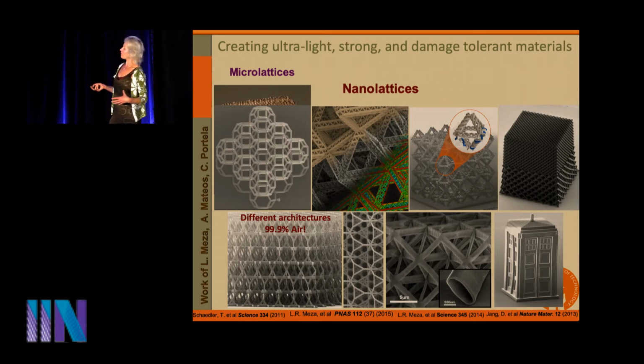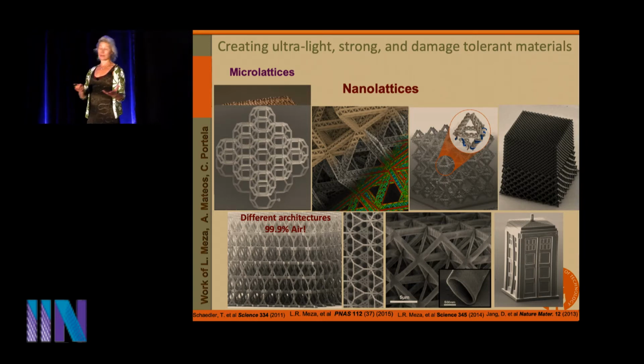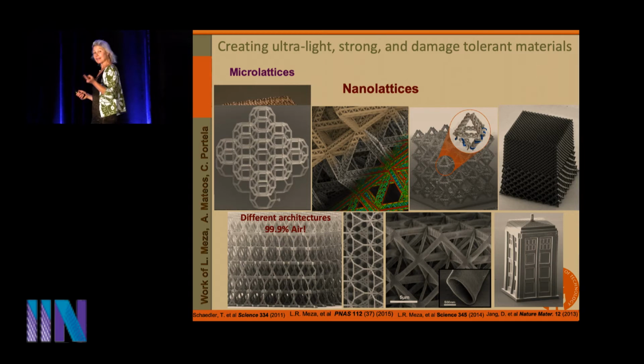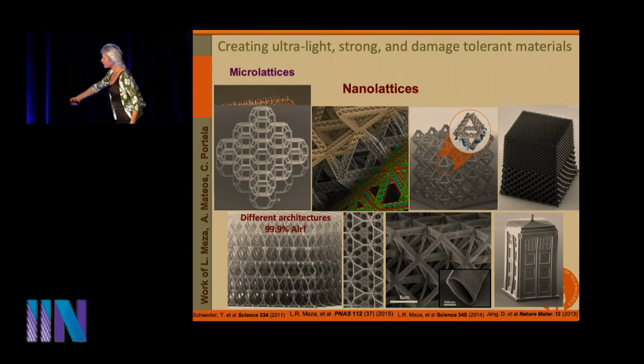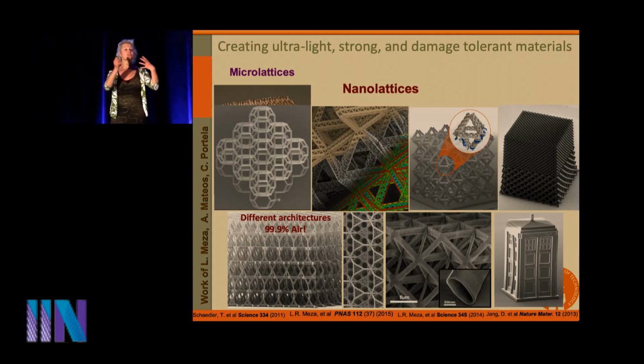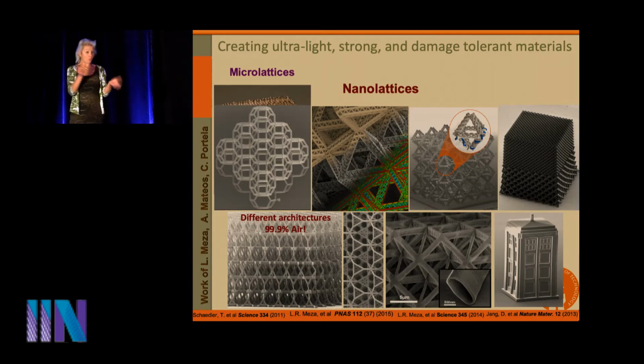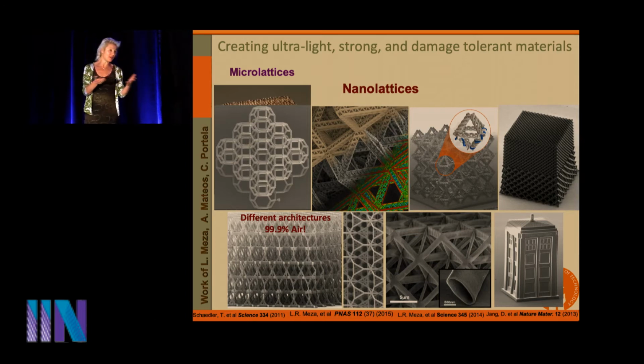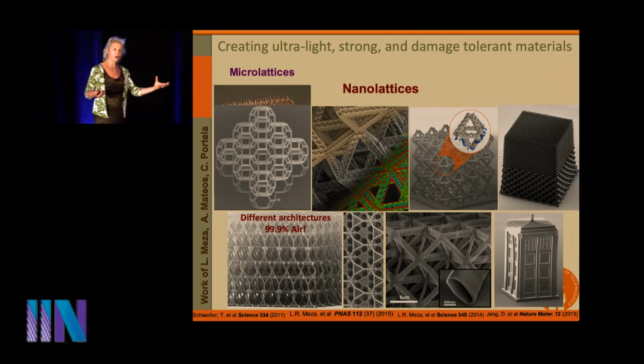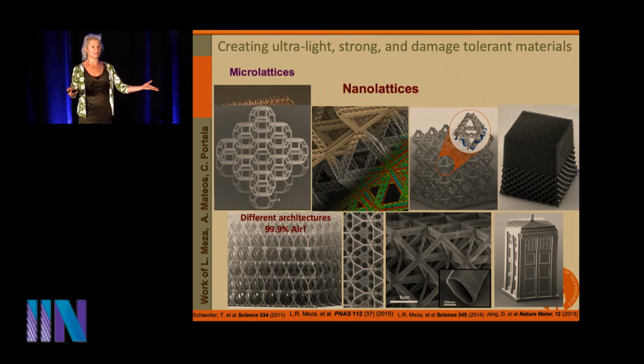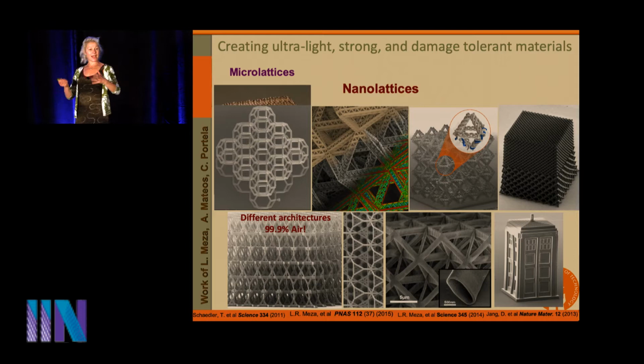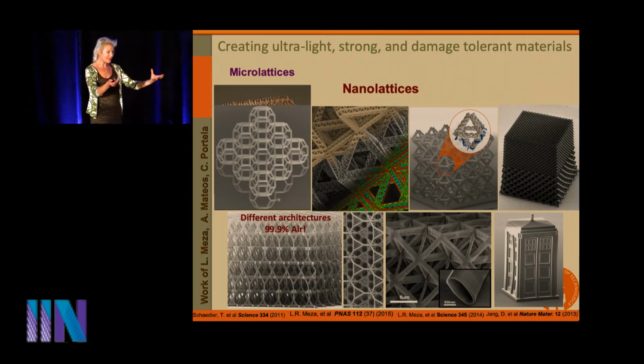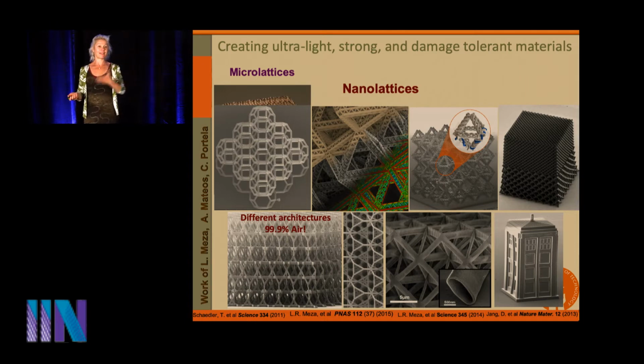There's an obvious level of porosity that you are observing, which is what gives them the lightweight, which is the fact that they're all cellular solids, so they're very open, porous structures. The slightly less obvious layer of porosity is this: the tubes that comprise these 3-dimensional interwoven networks are hollow. And the wall thickness of these tubes can be anywhere between 5 nanometers up to hundreds of nanometers. So the largest dimension in these solids, anywhere you probe, is just that wall thickness, which could be 5 nanometers. When you look at these materials and they sit on your hand, they look like a solid cloud or like an aerogel. But when you actually zoom in and try to measure anything within them, you realize very quickly that they're 99.9% air because of this.